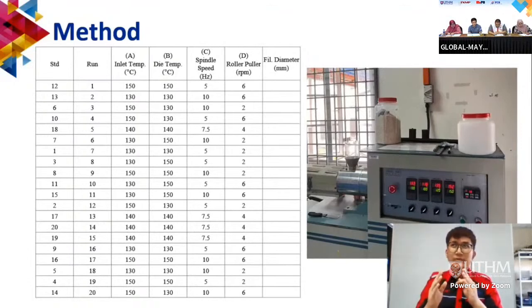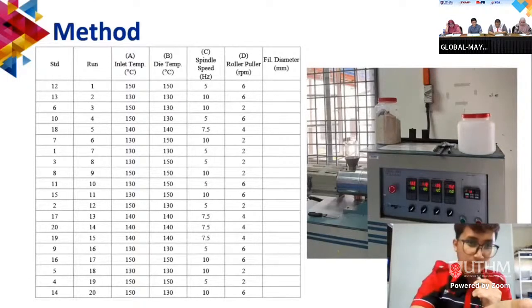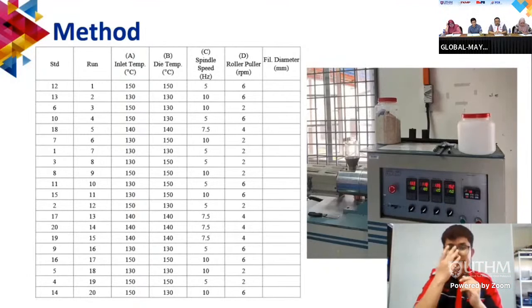People will ask where we got our temperature. We got our temperature using the PHA melting point, which is around 130 degrees Celsius to 150 degrees Celsius. So we put it in the inlet temperature and the die temperature. For the spindle speed and roller puller parameters, we use typical parameters for this extrusion machine. These 20 runs are generated from the Design of Expert full factorial.